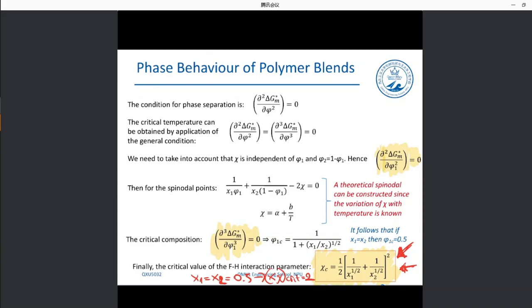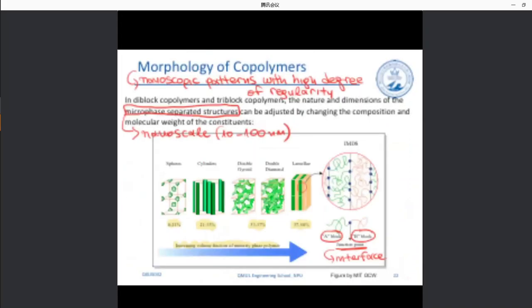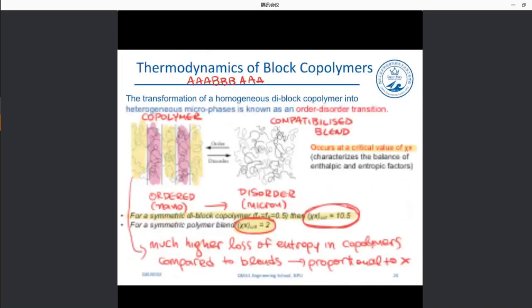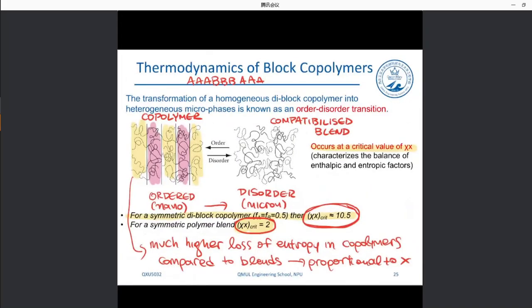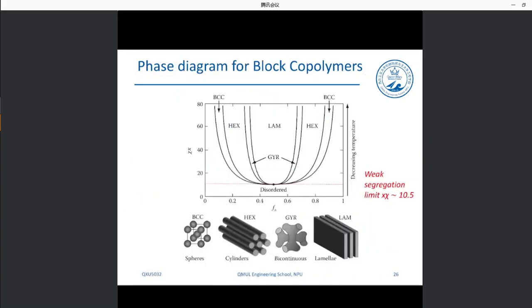It's interesting to see how much different these two products are for copolymers and polymer blends because of the loss of entropy in copolymers, okay? We still have a certain amount of entropy in copolymers, but the situation is much more ordered compared to blends. Now, let's have a look at the phase diagram for block copolymers.